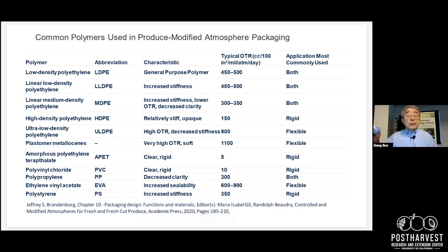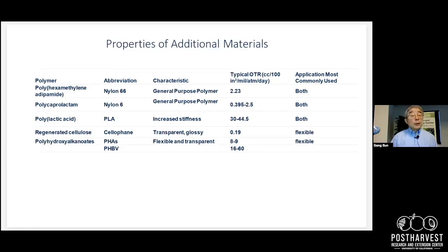But I also want to tell you that I did not find the thickness related information. Pretend this is all the same thickness for the same package, but this all comes from the source as a film, multi-layer films. Also, I tried to find more relevant data, particularly using the same unit of OTR. And I'm not good at converting, because there are almost over 10 different units for measuring the OTR. It's confusing. But finally, I converted them and spent some time, and I found out most of our natural polymers, or bio-based polymers, have very low OTR. So they serve as a good barrier.